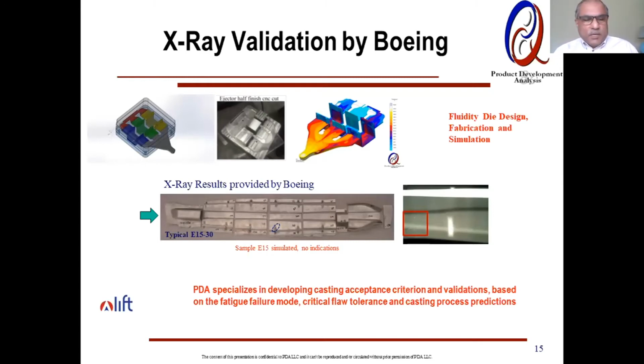cast. One thing we do, and I do talk about, is what I have seen in the metal casting industry is either over specifying the component by saying, hey, I want the entire casting level 1. When you do so, you really pay a price because it makes it very difficult to manufacture consistently level 1. What the suppliers end up doing is basically doing a weld repair if it's a weldable alloy, or if it's not, then you end up having a high scrap rate, and ultimately the OEM ends up paying for it.